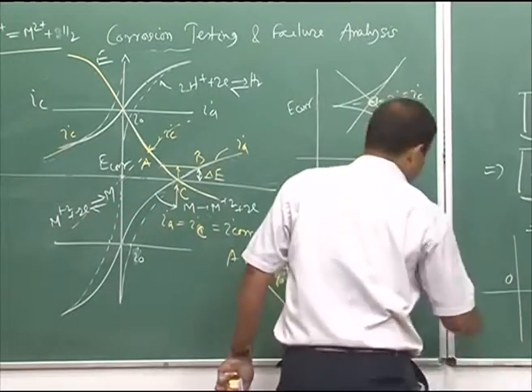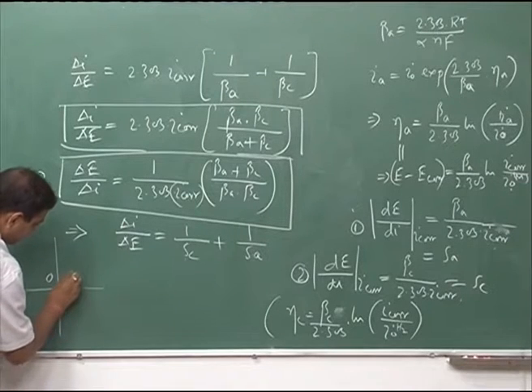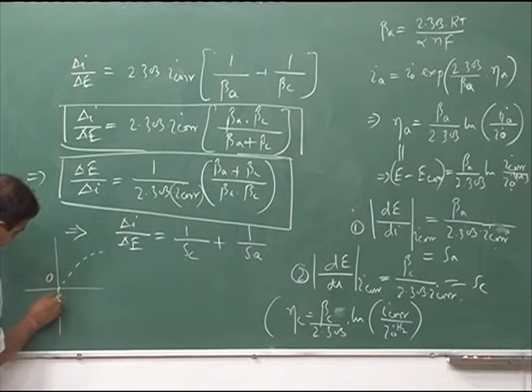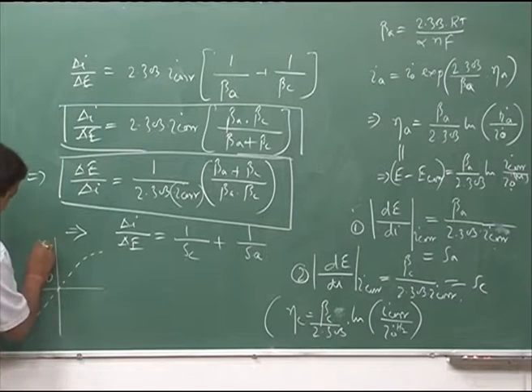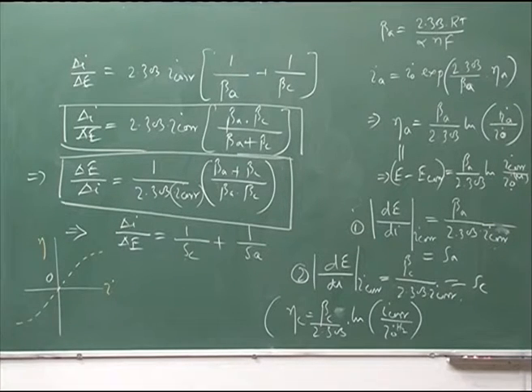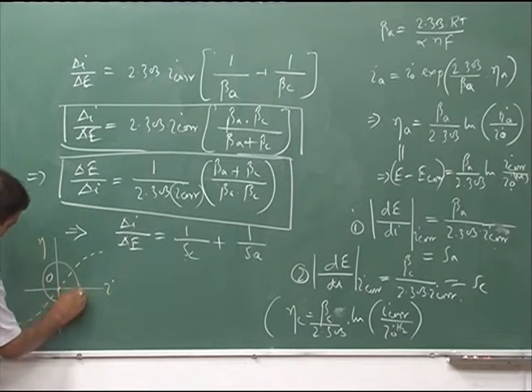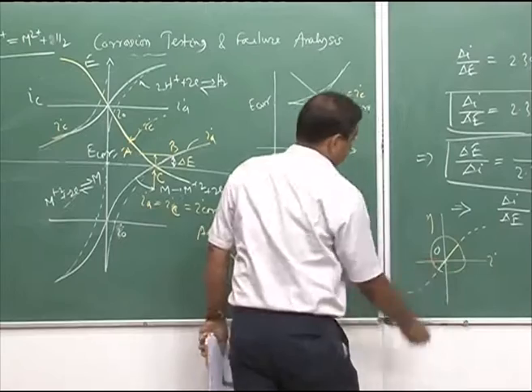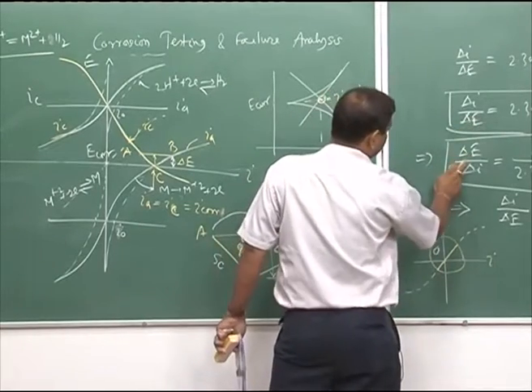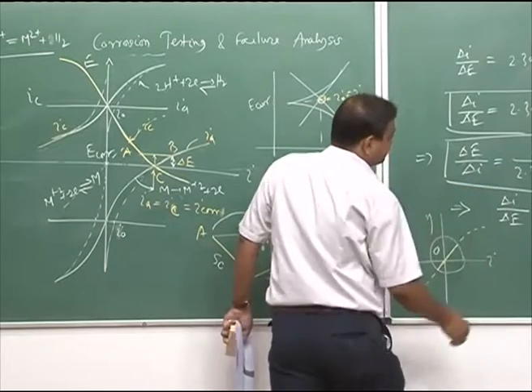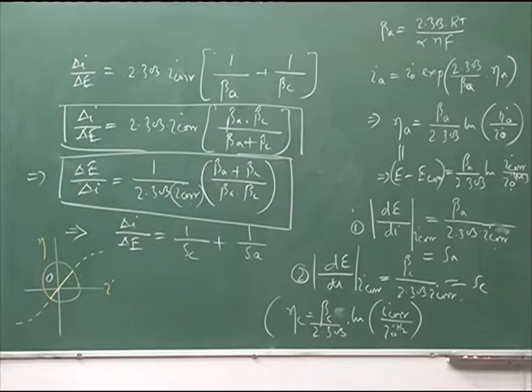So, the plot would be like this, and for the small over voltage, this line, we can find out the slope del E by del I, and from this expression we find out what is the I corr. So, this is the concept of measuring corrosion current density from linear polarization, and this is the linear polarization curve.